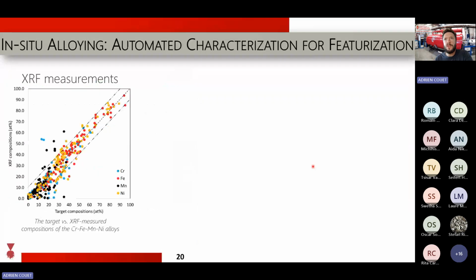So then we check the composition with X-ray fluorescence. We have an X-ray fluorescence gun that we can use to measure composition relatively quickly to see how close it is from the target composition. Clearly, it's not very close, but we don't really care because we just want to populate the tetrahedra. We're not really looking at, I want this alloy with this composition, right? The idea here is to populate the overall tetrahedra.